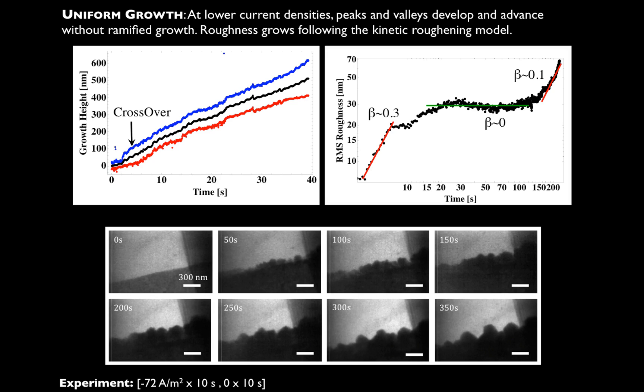What that is due to is some wave selection going on. You can see at the very last frame in the bottom right that there is a very obvious wavelength that has developed throughout this experiment. Even though early on we had a randomly rough surface based on the lithography of the platinum electrode, at the very end we see wave selection because of the interplay between the desire to deposit and surface diffusion.